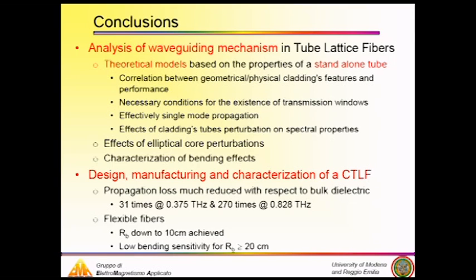At the same time, we have also considered perturbations of the ideal structure, such as undesired or desired effects for an elliptical core perturbation, and also bending effects have been characterized as well. Finally, during this last year, I was able to design, manufacture, and characterize a real fiber, showing that these hollow core waveguides allow strong reduction of the propagation loss with respect to the bulk material, and they also have a very low sensitivity to bending, for bending radius larger than 20 centimeters.